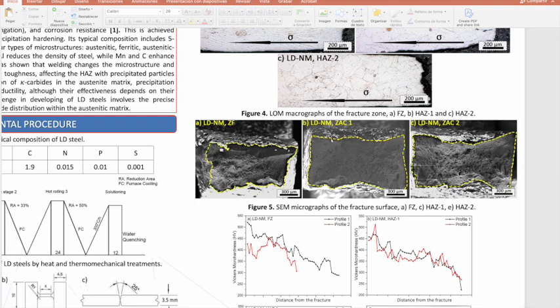On the other hand, Figure 5 subsection C, corresponding to HAZ2, is a zone with a higher concentration of κ-carbides, but there are more flat areas with sharper peaks. As a result, this zone exhibits the lowest elongation percentage but the highest strength.